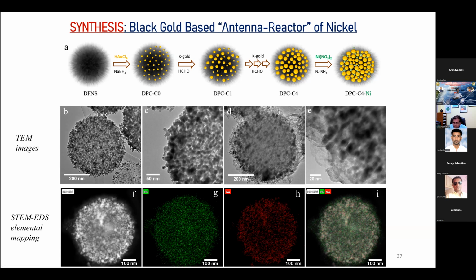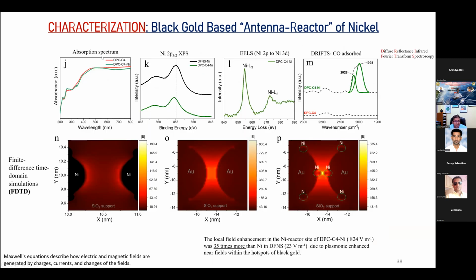We also wanted to know whether there is a change in the light absorption behavior of black gold when we load it with nickel. DPC is another technical name for black gold, dendritic plasmonic colloidosome, known as black gold. Now you can see when I loaded the nickel, there is no change in the light absorption. It's still a broadband light absorption.